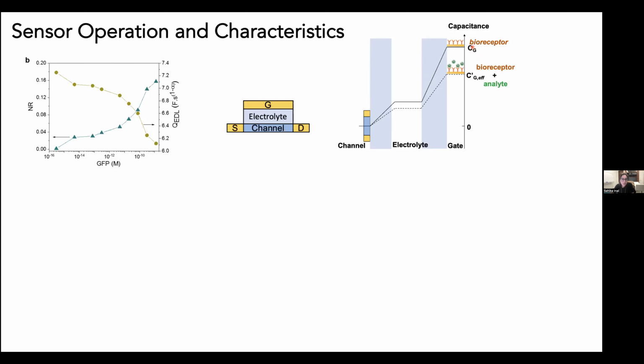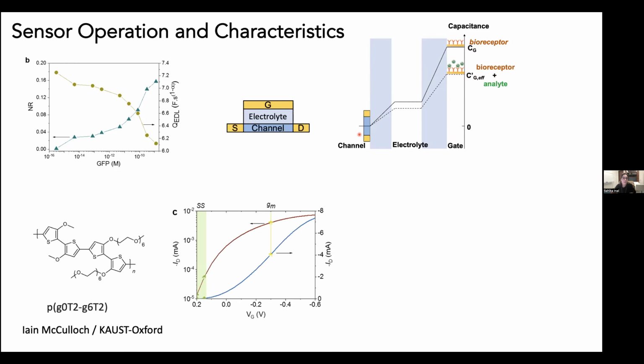And as the gate electrode capacitance decreases, this modulates how much current we are modulating in the channel. So it affects the ionic flux and how much ionic flux the channel feels. And because the devices are very sensitive due to their high transconductance, we do see very few binding events, which normally cause very small changes in the gate capacitance, cause a large change in the drain current that is flowing. And to be able to do that, again, we need to go to polymer chemistry and build devices that have very high transconductances. And we get these materials from Ian McCulloch's group at Oxford. And these materials, these organic semiconductors, give us devices that have very high transconductances and very steep, what we call sub-threshold slope, meaning that very small voltage changes at the gate electrode will cause a very huge change in the drain current. So we specifically engineer these polymers and use them in devices.